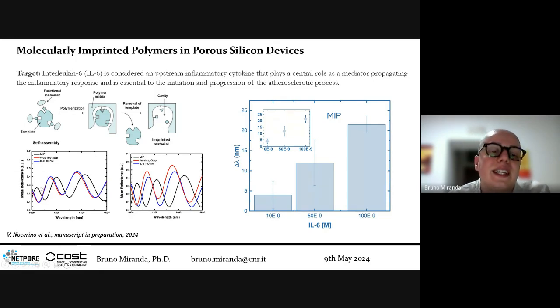These are very promising results. With the molecularly imprinted polymer, we have a red shift of the reflectance spectrum. Then we have the washing step, giving a blue shift because we are removing the template from the molecular imprinted polymer. Then we have increasing concentrations of interleukin 6 that cause a further red shift.